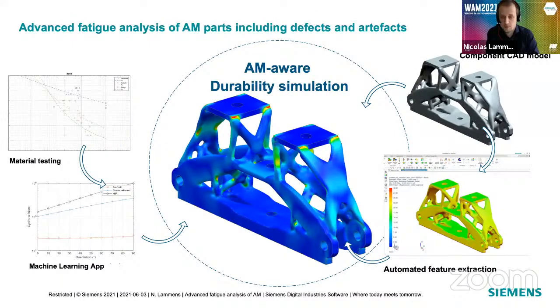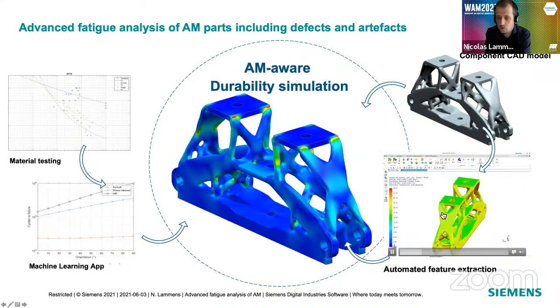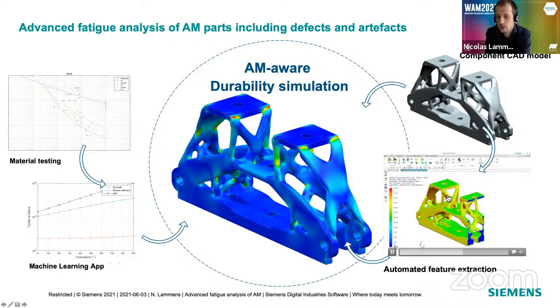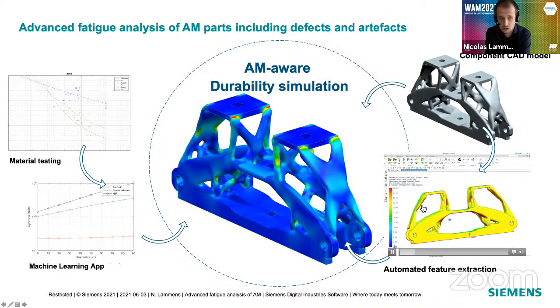So the idea we developed, and are developing, is an AM-aware durability simulation. And the concept that we use here is that on the right side, you start from your CAD model. And because we are 3D printing, it's more than likely that this CAD model is available. So that's already good. And with that CAD model and knowing how we want to print, we can go towards automated feature extraction. So that's what you see here. It's a simple example that we did where we predict surface roughness based on the orientation of the component within the build chamber. So those two we feed to the durability solver in order to know the geometry, the loads, and also all these features that I discussed.